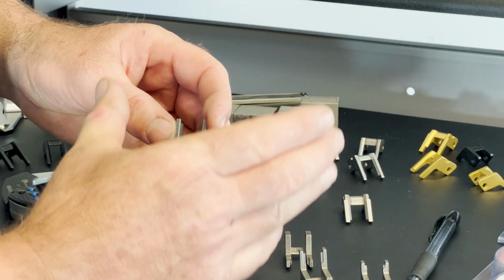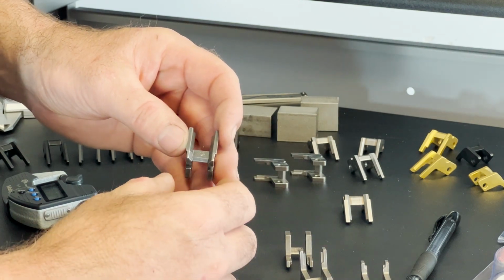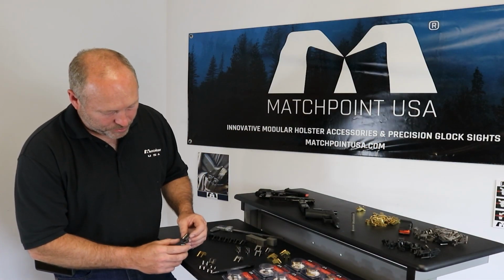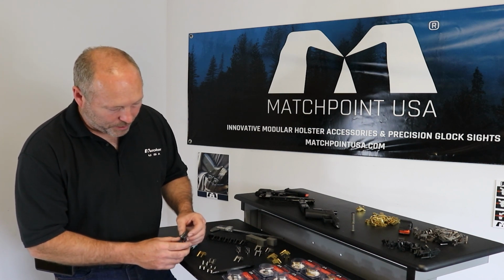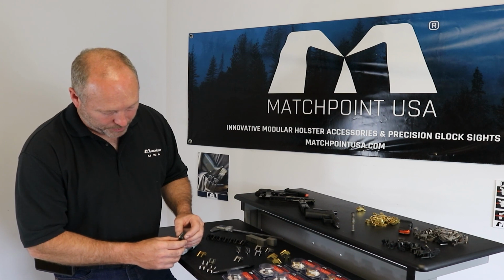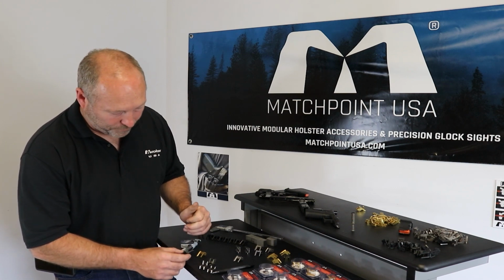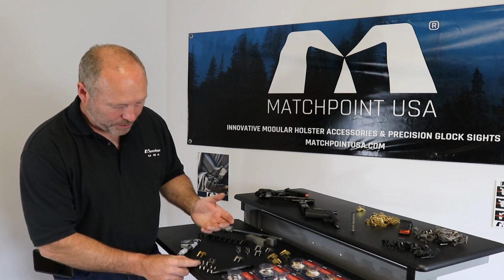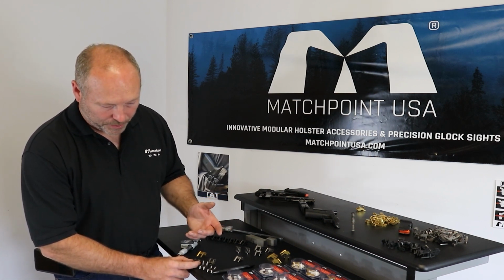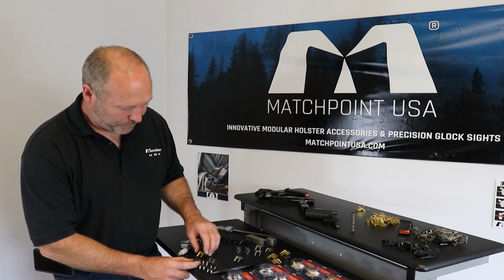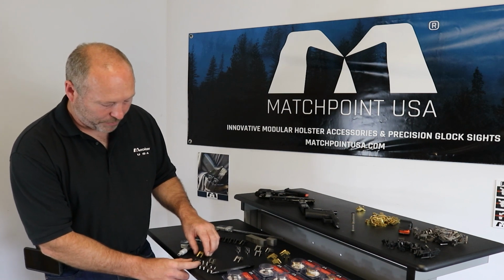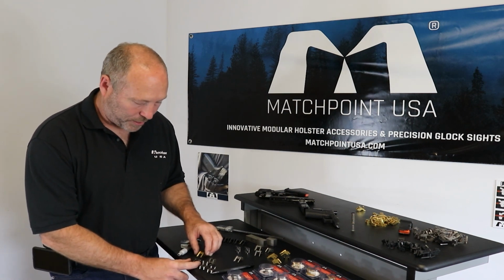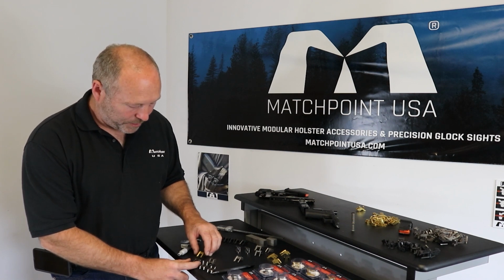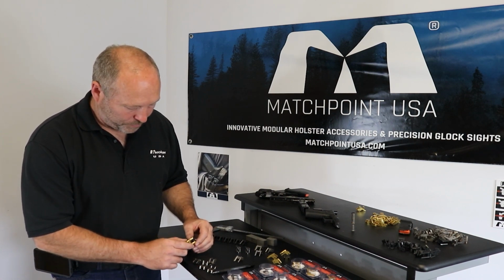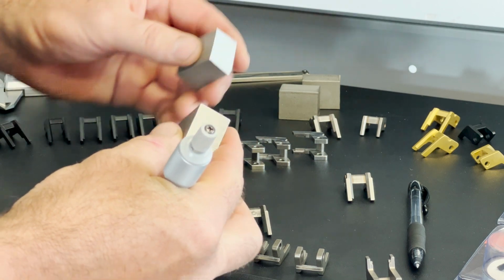Anyway, when the sintering happens, this thing shrinks 20.6%, which is a lot. This part's quite a bit larger. So it does leave voids. It's not 100% dense, and you have weaknesses as these break quite often. But it's a process that Glock pretty well has to use to keep the firearms within a reasonable price range. They can't possibly CNC machine everything they make. So we're not trying to knock their product. It's a great product. But it does leave room for improvement for aftermarkets, and we appreciate that. So back to the MatchPoint USA products.